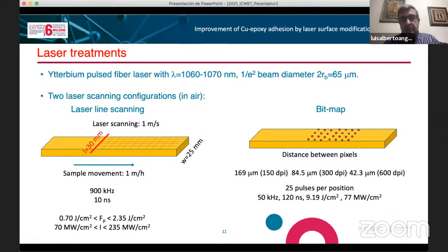For the laser treatment, we have been using an ytterbium pulsed fiber laser in the near infrared region, with a beam diameter of the order of 65 microns using the 1/E² criterion. And we have been working with two laser scanning configurations. The first one is the laser line scanning. In this case, the laser makes a line perpendicular to the section of the sample while the sample is moving in the perpendicular direction. So at the end, all the sample surface has been modified by the laser.